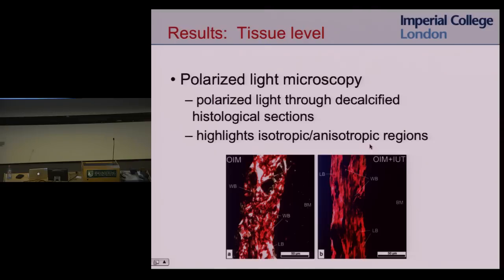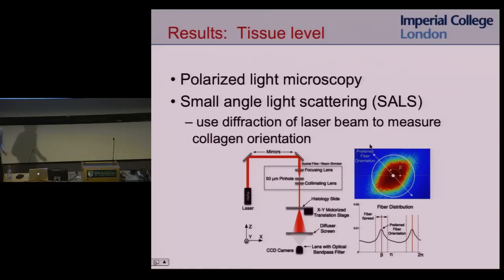So you can see it with your eyes, but it's really hard to quantify using polarized light microscopy. So right now we're using small angle light scattering, which uses a diffraction of a laser beam, to try to quantify how organized is the tissue. So basically you shine a laser beam through your decalcified section. It gives you some measure of the diffraction pattern. The more circular this is, the more isotropic it is, the more elliptical it is, the more anisotropic it is. So for organized collagen, we would expect it to be anisotropic or elliptical shape.